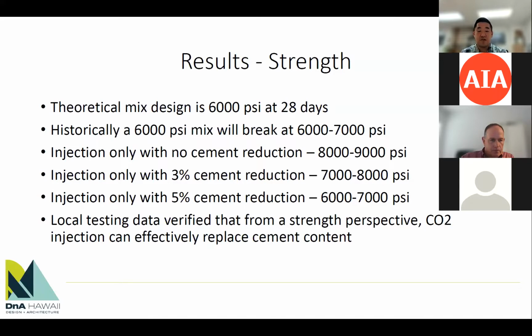So we actually took data for all the different products, and with injection only, with no cement reduction, we're actually getting 28-day breaks at 8,000 to 9,000 PSI. With injection and 3% cement reduction, we're actually getting in the 7,000 to 8,000 PSI range. And the optimal, which we realized through the course of the construction, the optimal design is to inject the CO2 and reduce the cement by 5%. And we found through the course of this project that it actually achieved that. Hawaii Concrete can basically, 6,000 PSI can achieve it with a 5% reduction and a Carboncure injection. So this was an awesome conclusion we drew.